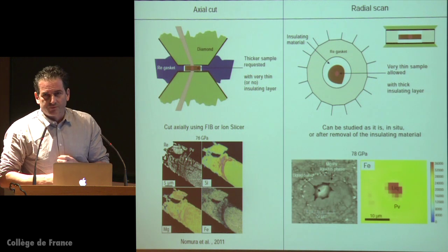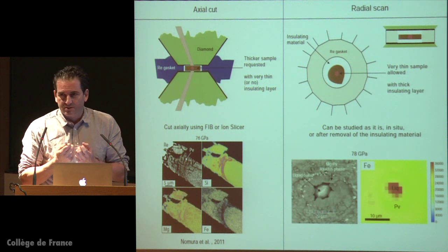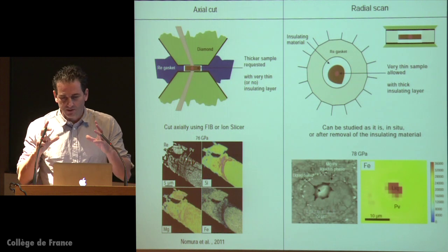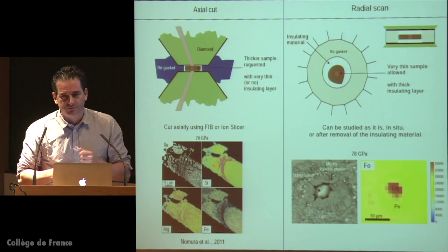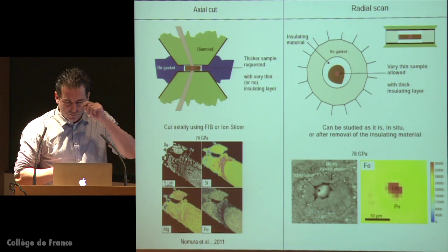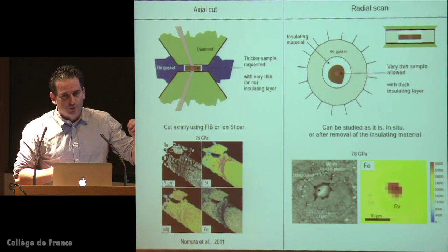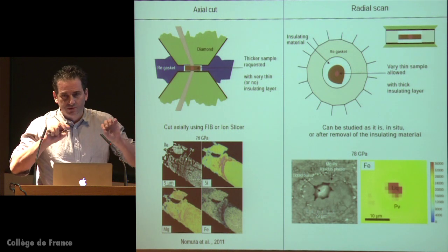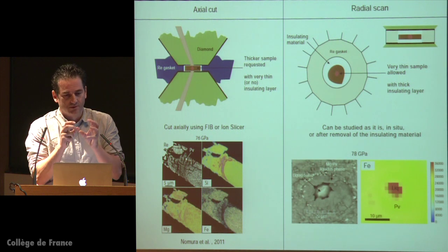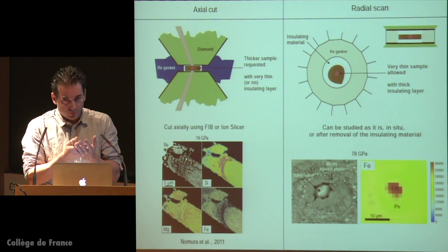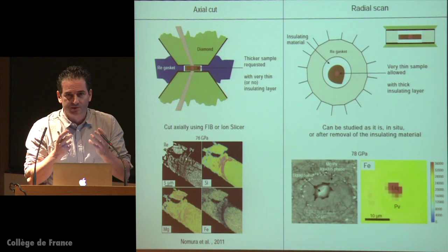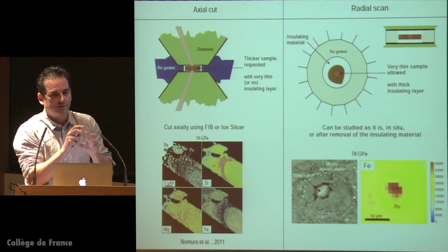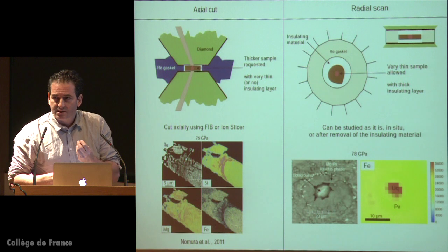In terms of the quenching of your melt, this changes completely the picture. Because if you have here a melt, then when you quench, and this has been demonstrated for experiments at low pressures, when they analyze the mantle, how it is produced, and how to produce 3%, 5% of the liquid, you have to take the liquid out of the capsule by cracks in the capsule or something. You cannot measure the liquid composition at a low degree of partial melting from a quenched sample, because when you quench, you start recrystallizing the phases that touch the liquid, and you get something at the end which you don't know exactly if it was the liquid.